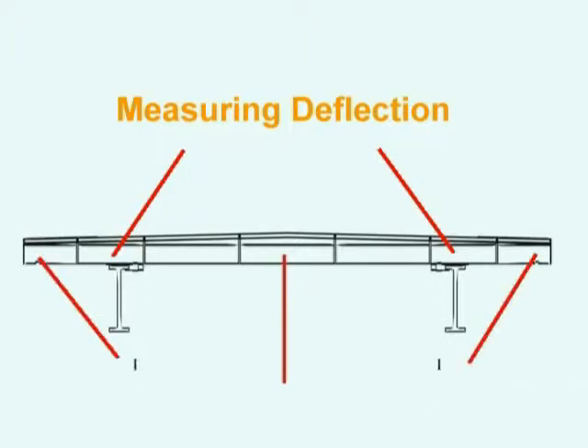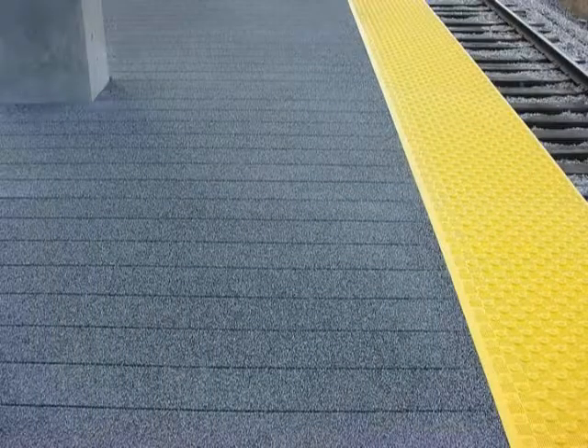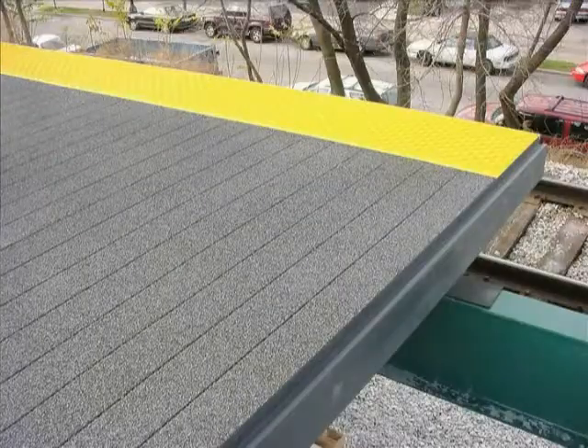The intent of this duration of this applied load was to verify that the material didn't creep while the load was held on it. And then at the end of the test, we monitored the deflection for another 24 hours to verify that the material did or did not return to a 0 point.